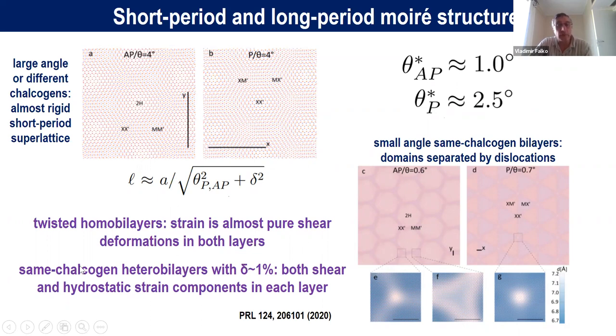And as I mentioned before, same-chalcogen heterobilayers have such small lattice mismatch that if we align them sufficiently, then the reconstruction of the lattice into 2H domains or XM and X' domains would take place, just because the long period of the superlattice allows for the adhesion energy to take over the energetic cost of the strain.